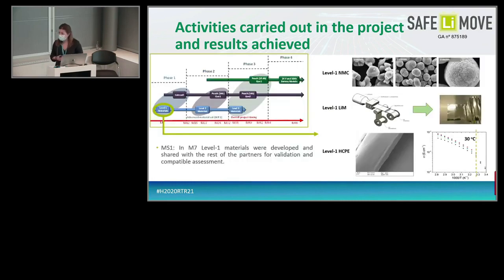So the first milestone of the project was reached in month 7, and in this case, we developed the first, the level 1 materials, where we have the level 1 NMC with high nickel content, level 1 lithium metal with a low thickness of 50 microns, and the level 1 HCPE. So in this case, the HCPE combines one type of inorganic material and one type of polymer material. These materials were delivered and exchanged among the different partners in order to study all the performance and assess the